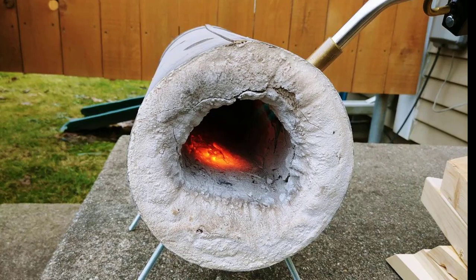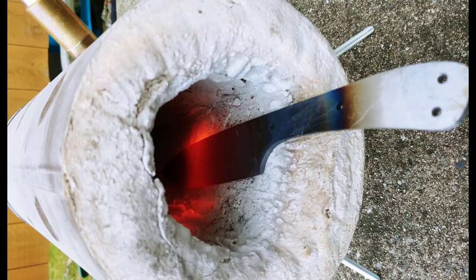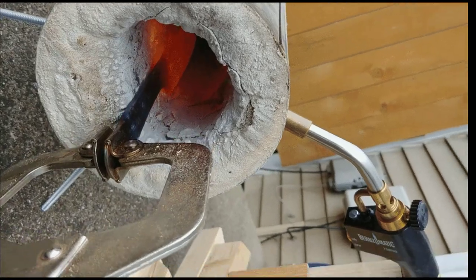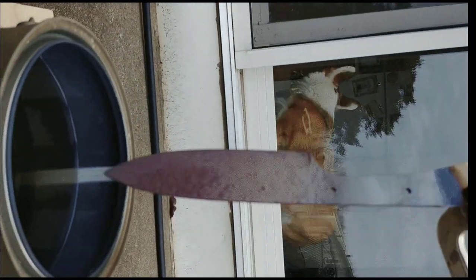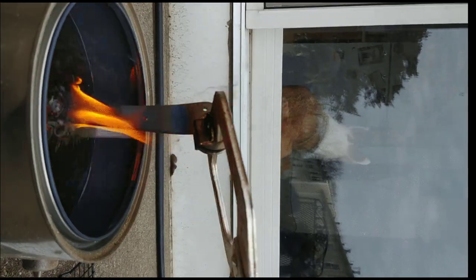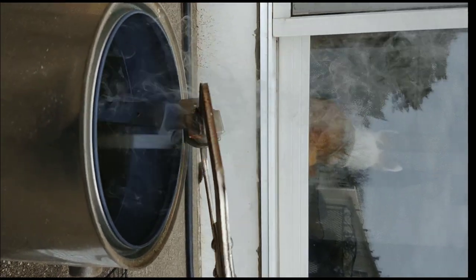Tip 1. For O1 tool steel, you will want to heat up the blade until it is not magnetic, 1500 degrees F. Just check it with a magnet until it no longer is attracted to the steel, and you will want to let it soak at that temperature for about 15 minutes. I've never timed it, but make it close. I quench mine in plain old canola oil that has been heated to around 125 degrees.